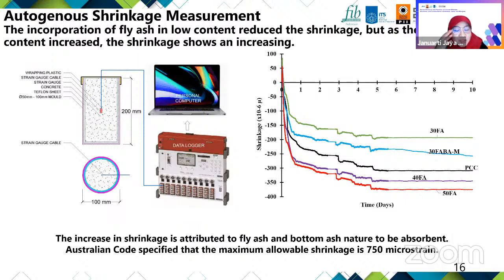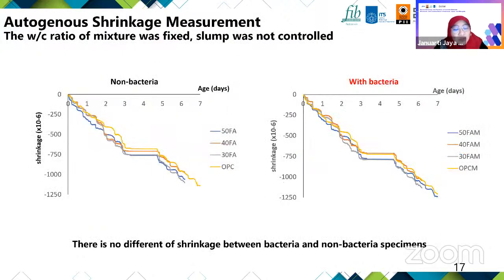And this is also very interesting to see that if we do not control the slump, we just keep the water to cement ratio constant in our mixtures to guarantee the moist curing, and we have to guarantee the moist curing up to 10 days. We found that there is no difference using 30%, 40% and 50% fly ash as a cement replacement compared to the control specimens. And there is a report that using microbes in concrete, the right side, doesn't affect the shrinkage. So there is no difference using bacteria or non-bacteria in the shrinkage measurement.